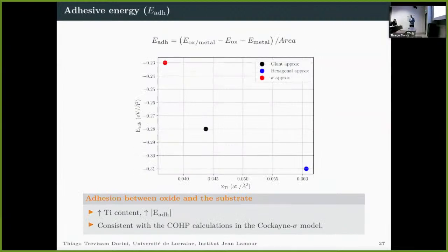And finally, I would like to highlight one interesting property of these phases. When we calculate the adhesive energy for the 3 phases, its adhesive energy increases when we also increase the amount of titanium per angstrom square in each of these approximate phases. And this is consistent with the COHP analysis that we have done for the Cockayne-sigma model, where we have seen that when you have more titanium bonded to the platinum atoms, it may correspond to a higher adhesive energy between the oxide and the substrate.